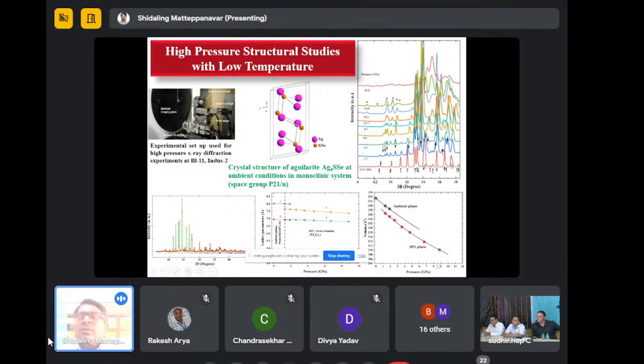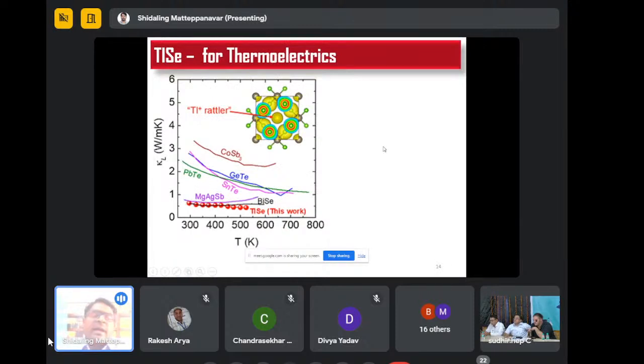So even when you are applying the pressure, it is going from the monoclinic to orthorhombic structure. And the next material that comes is the thallium selenide (TlSe) single crystal. For this material, for the first time we have observed such a low thermal conductivity in this sample.